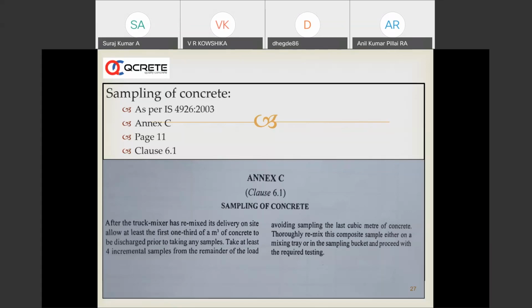Actually, one of the things is that the concrete has to be sampled in a very specific and systematic way, as discussed and exhibited in a standard. For example, IS 4926 very clearly says that when the truck reaches the site, the drum has to be turned at high speed to mix, and then you have to leave about 0.3 cubic meters of concrete onto the pump, and after that you take the concrete sample for slump and casting cubes.